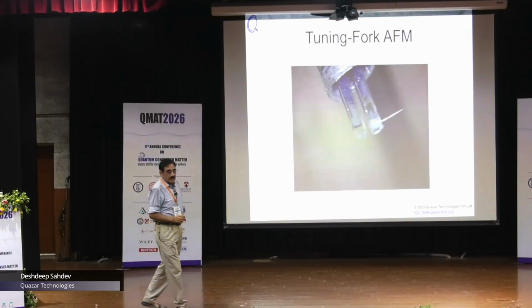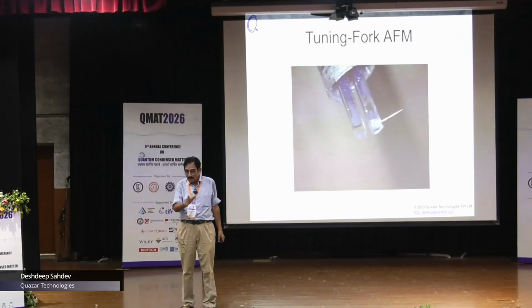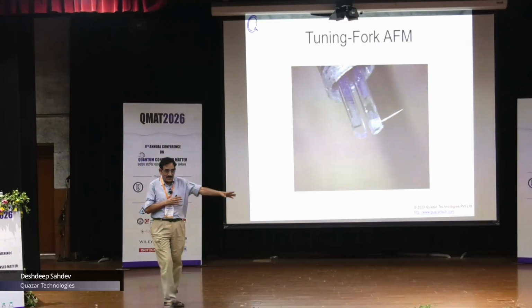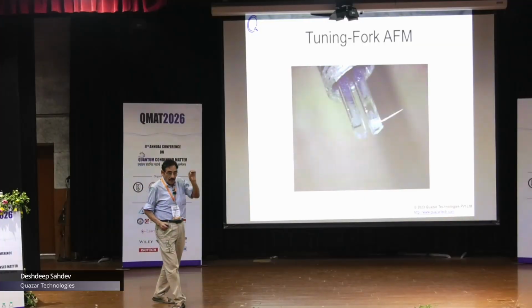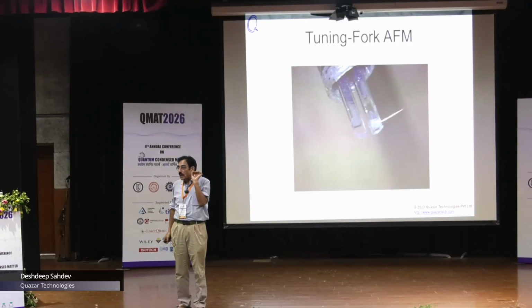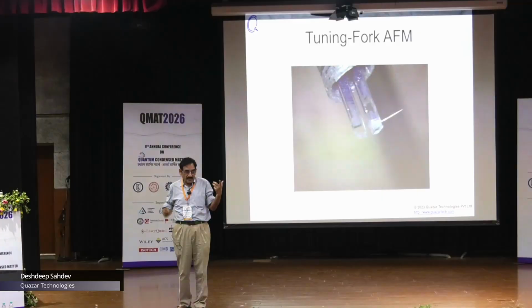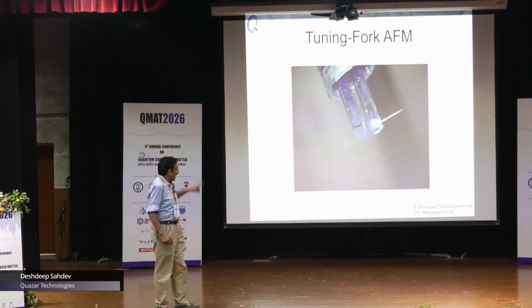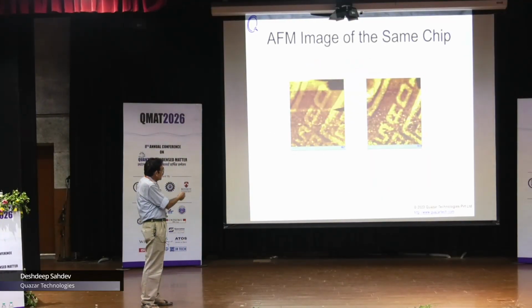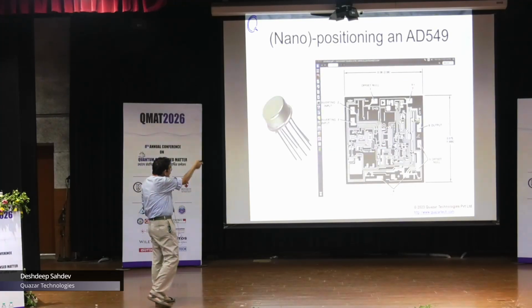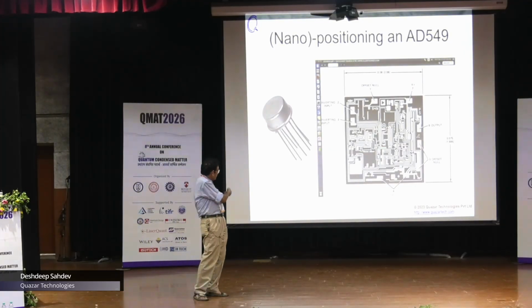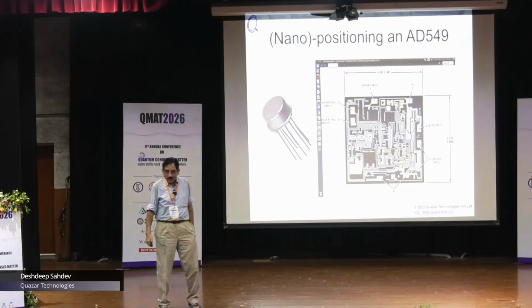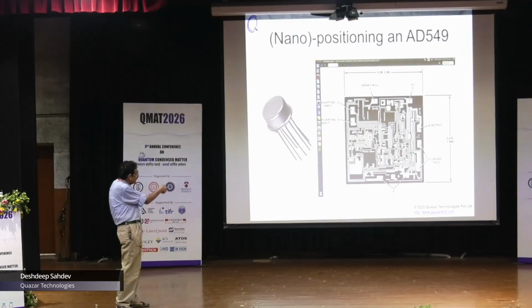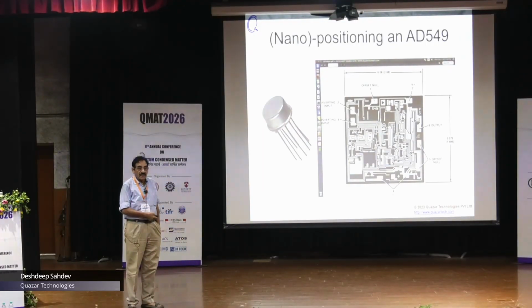And then using a lock-in amplifier, which also we designed and made, according to the same philosophy, we were able to pick out changes of only 1 part in 10 to the 7. It's a few millihertz in 10,000 hertz that we could pick out. And using that, interestingly, what we did was that we opened it out, this is an AD549, and you can see this 1985 ADI, which is Analog Devices Incorporated. It's written on top of it. This is the top layer. This is something we got from their website.